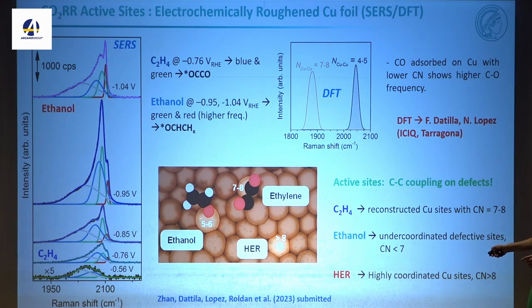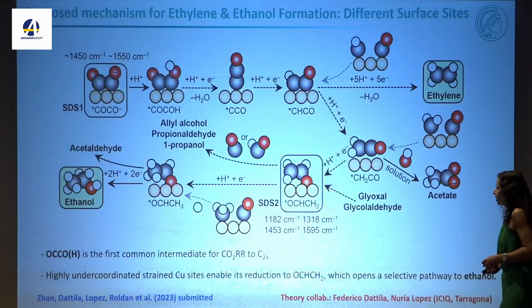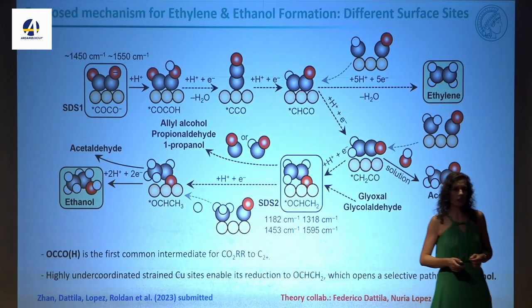And for the calculations, it seems that when we have the lowest coordination, and better if there is some oxygen around, then you favor the production of ethanol. And this intermediate coordination helps the CC coupling to make ethylene. And this is also made on metallic sites. So you can propose a model like this.